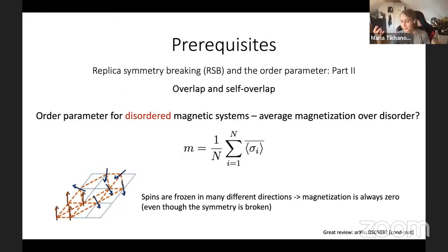Now, one would think that the natural order parameter for disordered systems would be a similar thing, but just averaged over disorder, right? So that would be correct, except as I mentioned, when you go through the phase transition and you end up in a spin glass phase, all your spins are frozen, but they're frozen in a weird configuration. And you cannot predict that, right? So it's not an ordered state, it's a random configuration of spins. Therefore, when you take the average over all of it, you'll end up with 0. So this is just not a good order parameter.